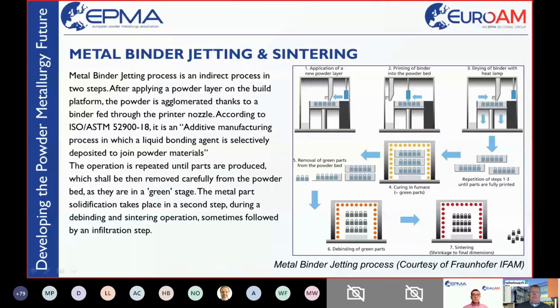As we know this from standard powder metallurgy, you end up with green parts being printed. These green parts, together with the whole building block, are then cured in a furnace, and then you can remove these green parts out of the powder bed. You can also reuse the powder to a certain extent.